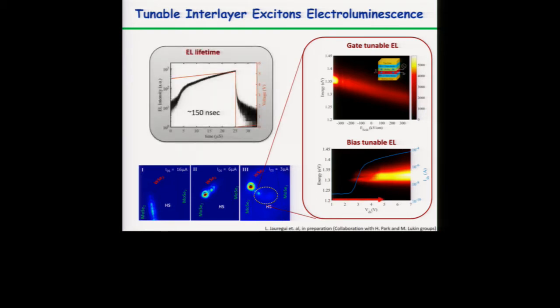And if we measure the lifetime of this electroluminescence exciton, which is a tunable interlayer exciton, the lifetime is also long. It's around 150 nanoseconds. So we can generate them electrically, we can tune the energy with the control that we have with the top and bottom gates, and we can control where the emission comes from.